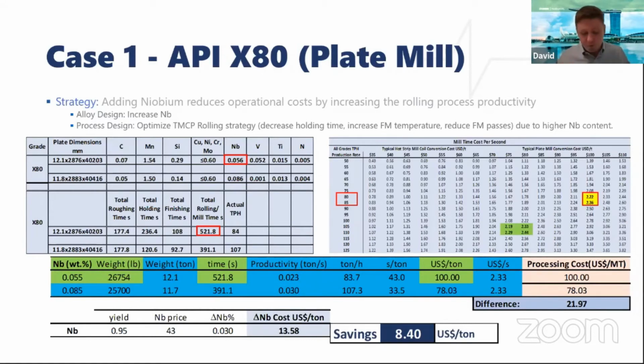And that mill did not operate at full capacity and considered the total cost with that productivity too high. So the engineers of this company were forced to redesign the alloy to reduce the total rolling time and try to improve the total tons per hour. And that was done by removing the vanadium and increasing the niobium to 0.085 addition. They could manage to increase the productivity to 107 tons per hour.